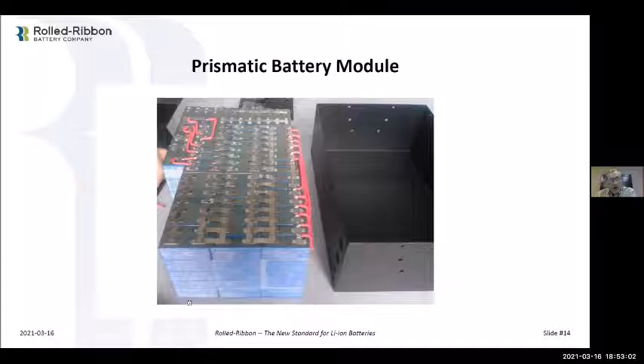If you want to cool it, you put a cold plate on the bottom here. But again, all you're doing is cooling the can, and the can just gets hot from the heat that starts from the terminal because it came up the tab and then migrates its way over the can. So very little effect back on the electrode, and the electrode is what is going to degrade under thermal stress. That's what gets destroyed by the heat.